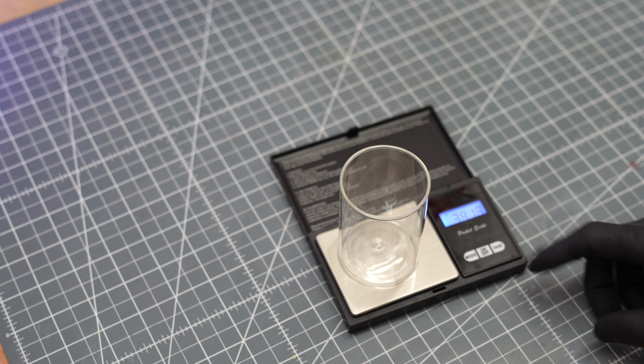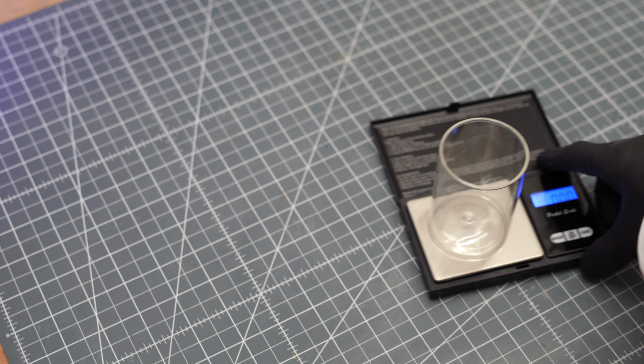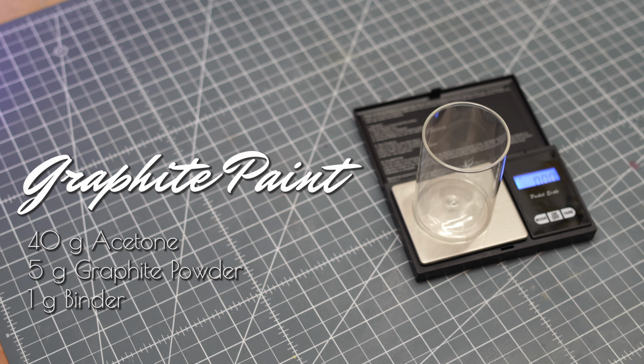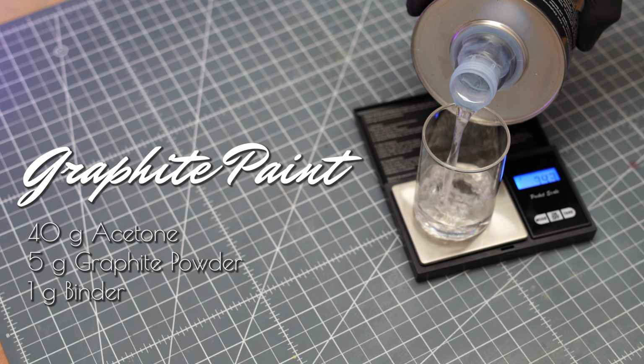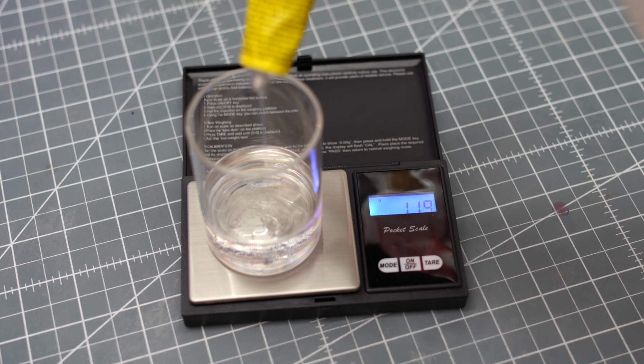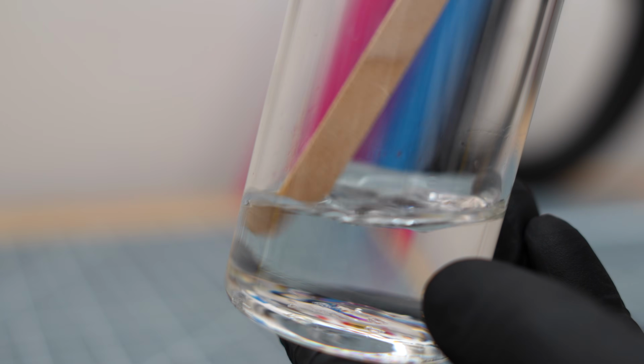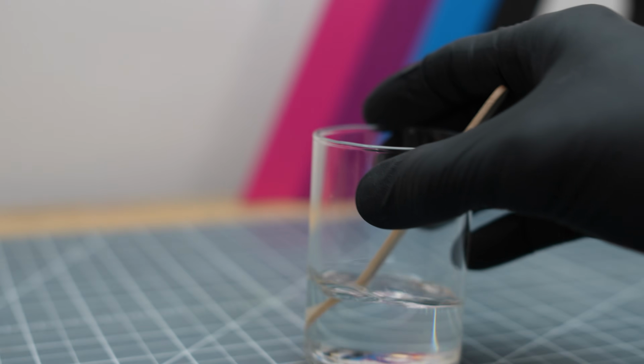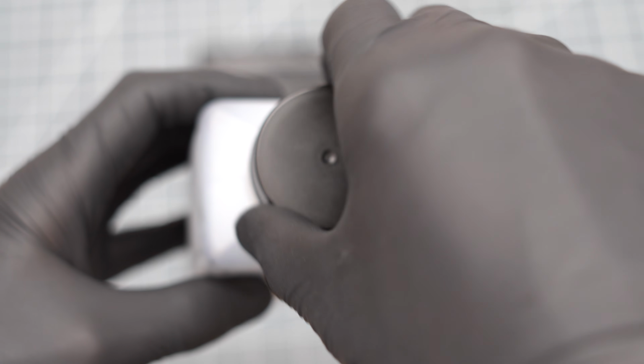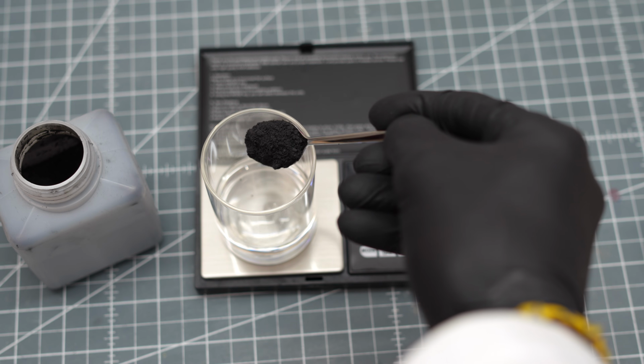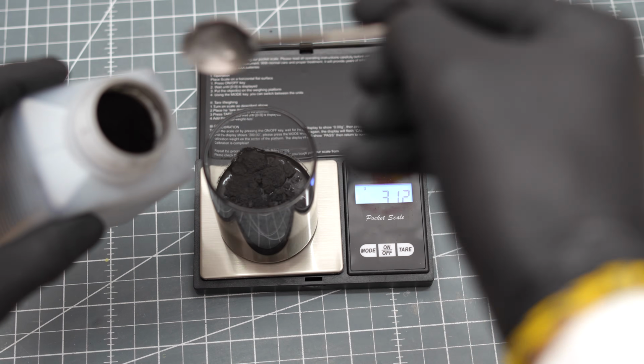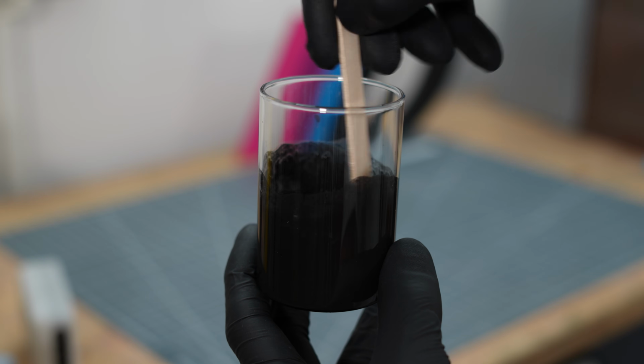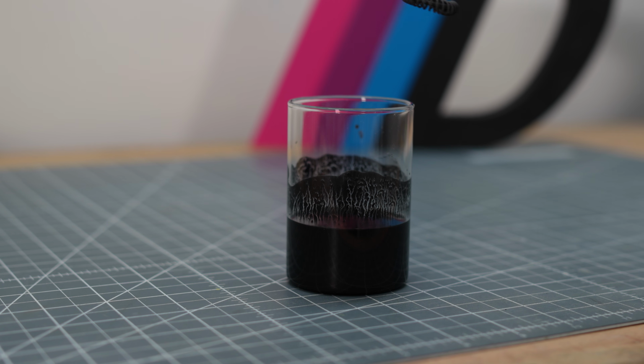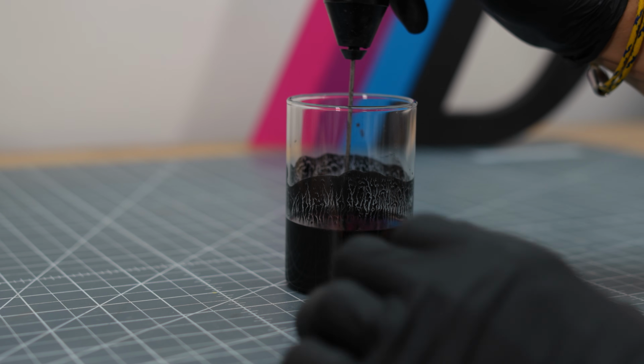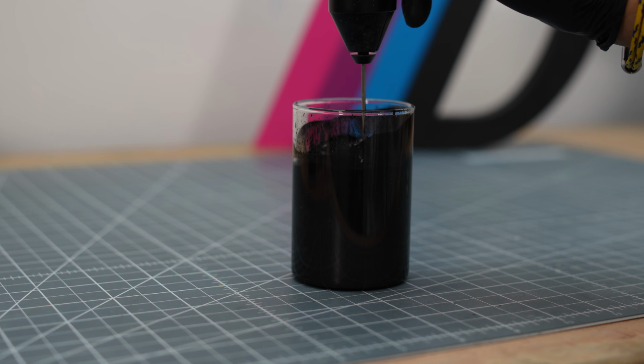So, the paint. I'm not claiming this recipe is perfect, but it's sprayable with an airbrush and works quite reliably. Take 40 grams of acetone and dissolve about 1 gram of binder in it. Let it dissolve properly. Now add 5 grams of graphite powder and mix it well. You can use an old milk frother like I have here, but I recommend against it for reasons.